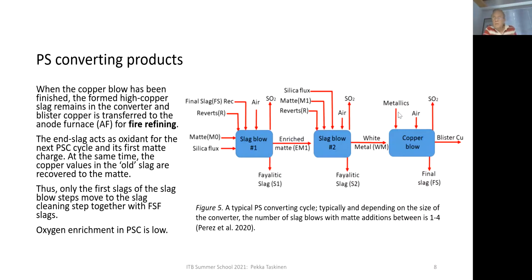Metallics like spent anodes from the refinery are used as coolant. These reverts may be low grade copper scrap or whatever, containing much less than 90% copper. They are refined there at the same time, but the coolants in the copper blow are typically pure anode copper, which is coming back as spent anodes from the electrolytic refining step.